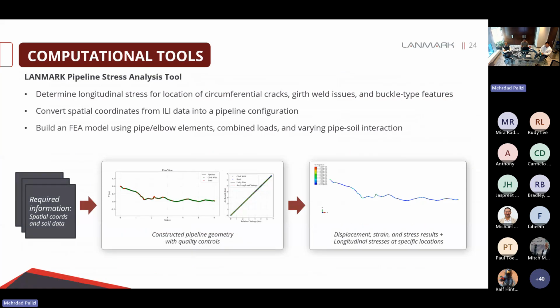In the case of some imperfections, let's say if we have a circumferential pipe body crack, a crack-like flaw over the girth weld, or buckle-type imperfections, the longitudinal stress is going to be the driving force and not the hoop stress. In these cases, it is essential to have an accurate assessment of the stress state at that feature location. This could be done using our AutoPipe, or at the same time, we can also use our internal pipeline stress analysis tool.